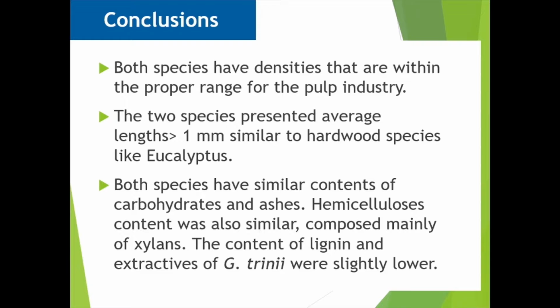Both species have densities that are within the proper range for the pulp industry. The two species present average length greater than 1 millimeter, similar to broadleaves such as eucalyptus. Both species have similar carbohydrate content. The hemicellulose content was also similar in both species, composed mainly of xylan, in the same way as the ash content. The lignin and extractive content of Guadua trinii were slightly lower.